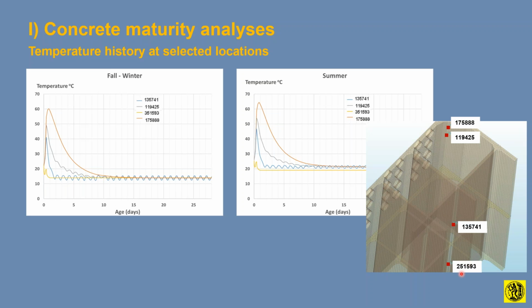And we can see that this node here, which is below sea level, practically starts at the delivery temperature and sinks and stabilizes to the sea level fairly fast. So within 2 days, basically this area of the caisson stabilizes to a concrete temperature, which is maintained by the sea level, of course. The same in the summer, but in this case, the temperature of the sea is much closer to the laboratory condition of 20 degrees, which gives us the lab strengths.